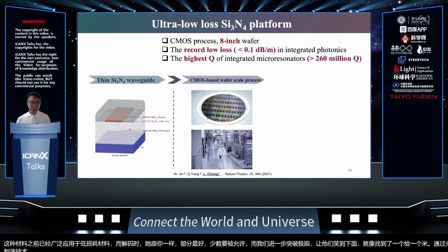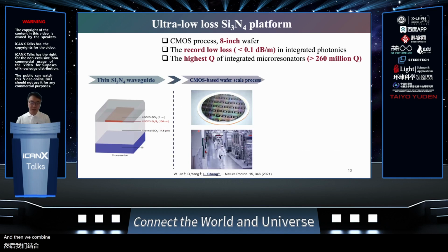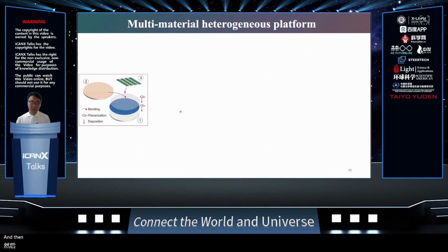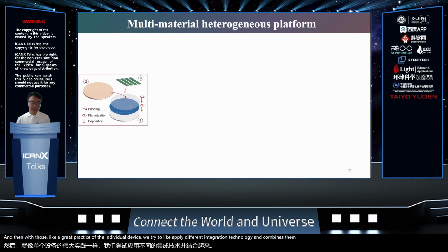And then we collaborate with photonic foundries and achieve an 8-inch low loss silicon nitride platform. On this platform, we achieve more than 260 million quality factor, which is a record among integrated photonics, and with very high yield over the entire wafer. With those great properties of the individual device, we try to apply different integration technology and combine them onto the same substrate.